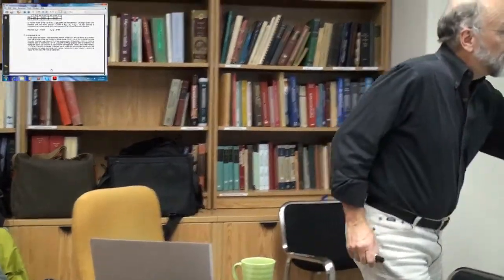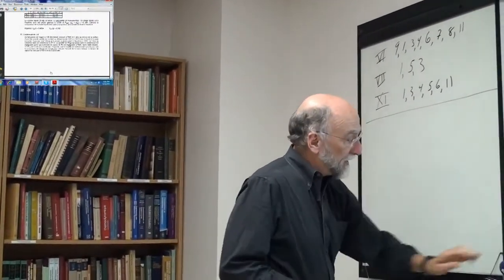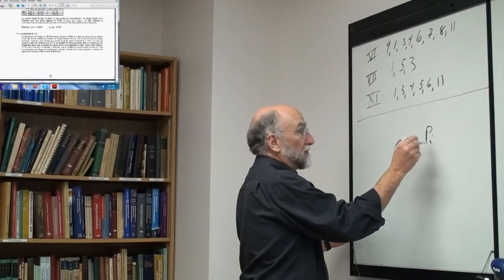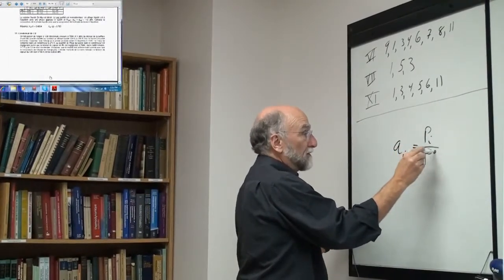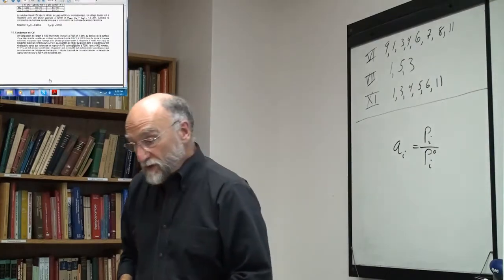Yeah, this is a way of measuring, if you see this. Okay, the activity: if you want to measure the vapor pressure, one way of measuring activity is by measuring the vapor pressure. So the activity of a component is its vapor pressure over the solution divided by the vapor pressure over the pure material. Okay, so there are different ways of measuring vapor pressure.